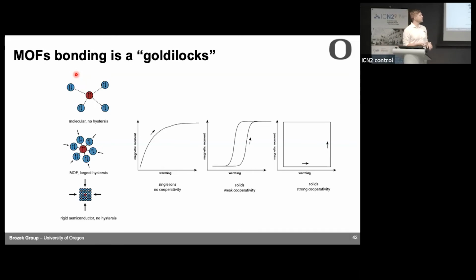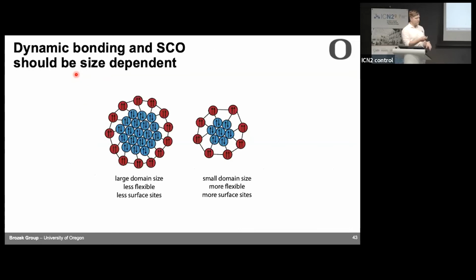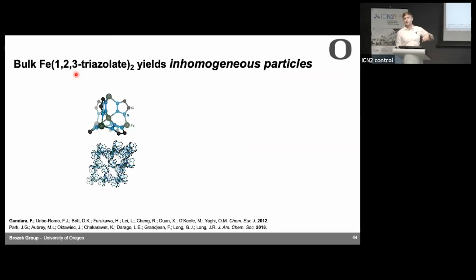People also predicted that this should be really size dependent, because in models of spin crossover, the magnetic centers that are on the outside are the most flexible. And so those are the ones that should go high spin first. We wanted to show that this was true. So we thought, well, let's take iron triazolate and try to make it as nanoparticles. And when you make iron triazolate the normal bulk route, the one that was reported,